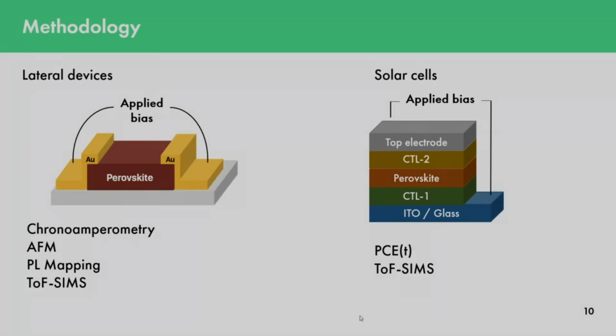It has a thin film of perovskite material, then gold electrodes evaporated on top, and we leave a small channel, not wider than probably 100 or 200 micrometers, for applying an electric field. The electric field is applied to these gold contacts, and some processes are observed inside this channel near the cathode, the anode, and probably in the middle somewhere. These devices we investigated with chronoamperometry measurements, atomic force microscopy, photoluminescence mapping, and TOF-SIMS, which is probably one of the most informative methods that we used in this work.